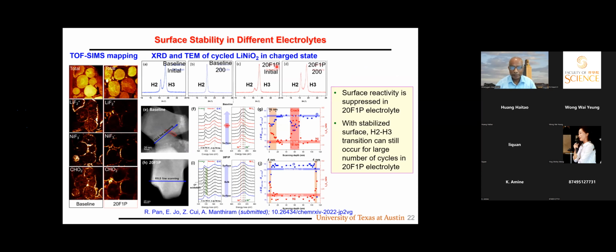In the case of the other electrolyte, which cycles well, you have H2-H3 phase transformation initially, as well as at 200 and 400 cycles. It is maintained. That's why there is more secondary particle cracking, because you are going through a lot of this phase transformation in this case, but it does not cause any primary particle cracking.